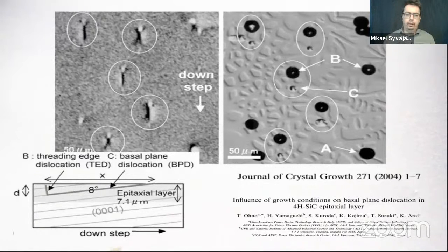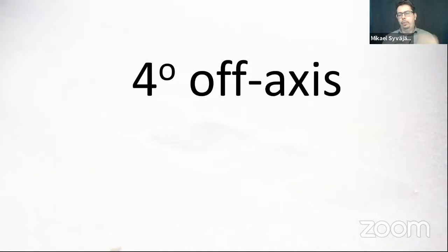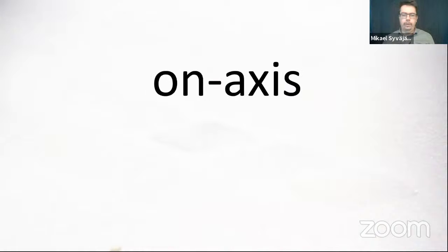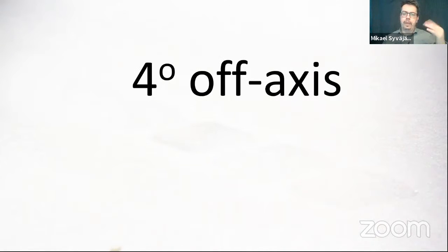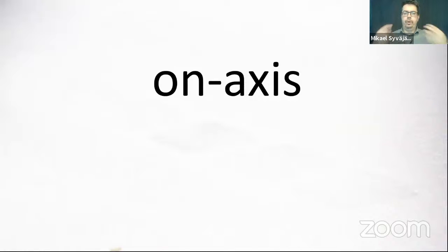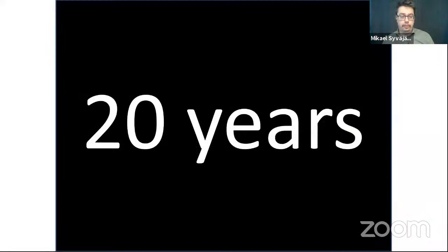So they always complain about the material guys. So what was done then was to make a compromise that you have 4 degrees off-axis 4H, and then you could have homoepitaxial layers. And what would be preferable would be to have on-axis growth without any problems for the 4H. And this road from the beginning, when you had the 6H and 3C inclusions, and then you changed things over time, it took 20 years.